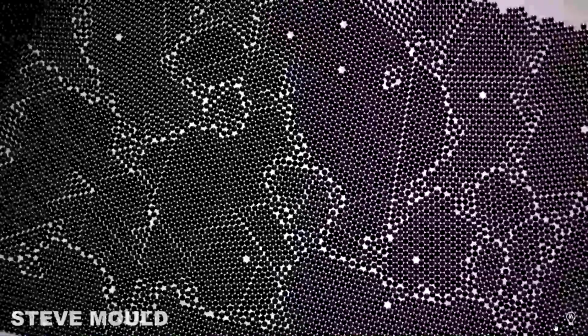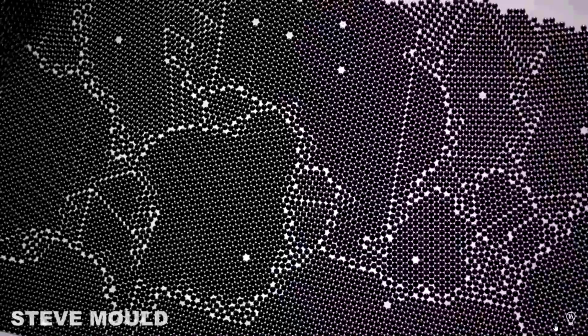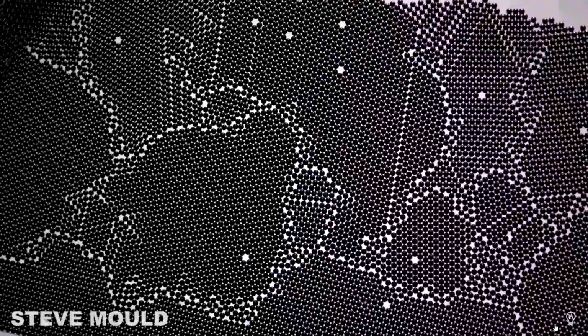So if your metal has small grains, then the dislocations within those grains won't have far to travel before their journey ends, before they reach a grain boundary. And on a macroscopic level, that means that your metal isn't very ductile. You can't plastically deform it very much. And if you keep applying force, then it's just going to fail in other ways. Whereas if you grow the size of your grains like we did here, then you're giving those dislocations further to travel. You're increasing the capacity of your metal to plastically deform before breaking. You're increasing the ductility of your metal.